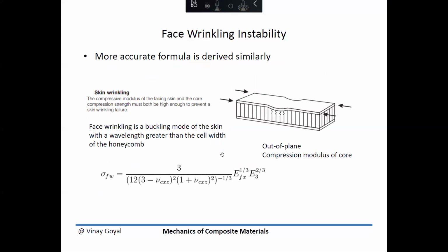More accurate formulas do exist. Here is one such formula. Nu here is the Poisson ratio, in this case the Poisson ratio of the core in the transverse direction, x z, like that. You also have it to the minus 1/3 power. This is the face sheet modulus to the 1/3, and E33 corresponds to the through-the-thickness modulus of the face sheet. And so you can calculate the face sheet stress that could cause wrinkling.